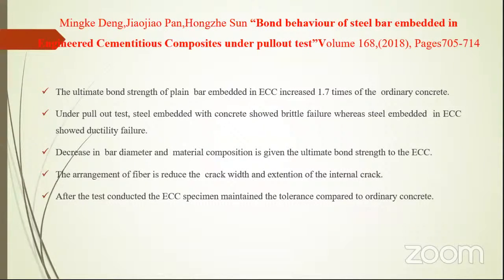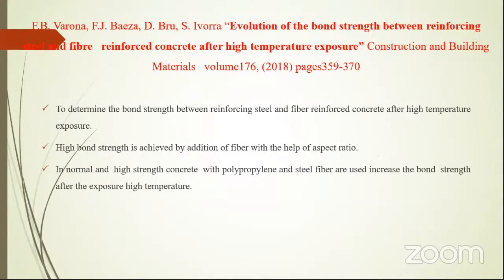The next paper is about bond behavior of steel bar embedded in engineered cementitious composites under pull-out test. In this paper, the ultimate bond strength of plain bar in ECC increased 1.7 times that of ordinary concrete. Under pull-out test, steel embedded in concrete showed brittle failure, whereas steel embedded in ECC showed ductile failure. Decrease in bar diameter and material composition give the ultimate bond strength to the ECC. The arrangement of fiber reduced the crack width and the extension of the internal crack. After the test, the ECC specimen maintained its tolerance compared to ordinary concrete.